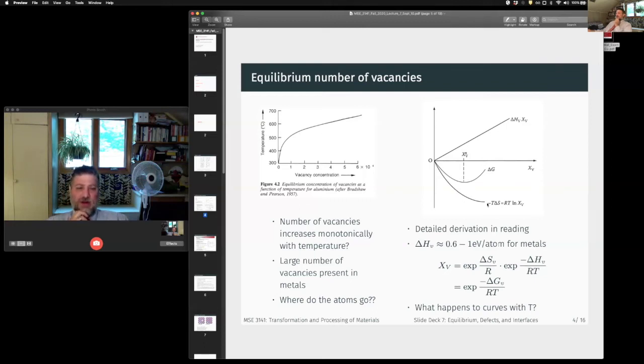So the enthalpy term is just linear and constantly increasing. However, the entropy term is really what's driving this, because there are a lot more configurations the greater the number of vacancies you get. Of course, it begins to saturate out. So what we have here is a monotonically increasing curve plus a monotonically decreasing curve that initially has a greater negative slope than our increasing portion.